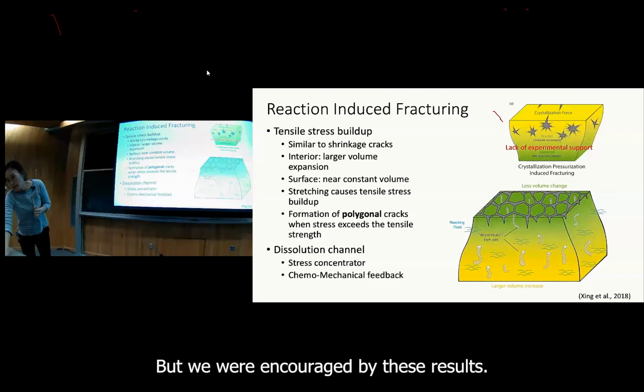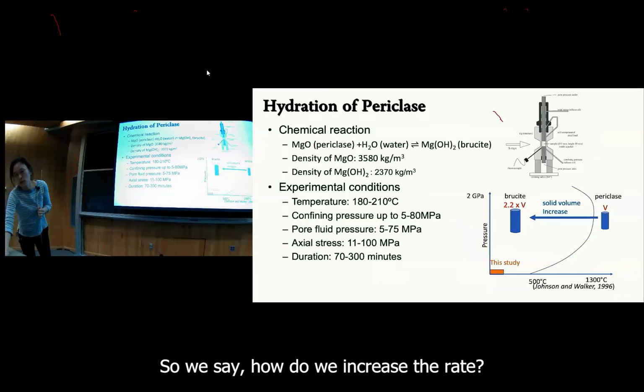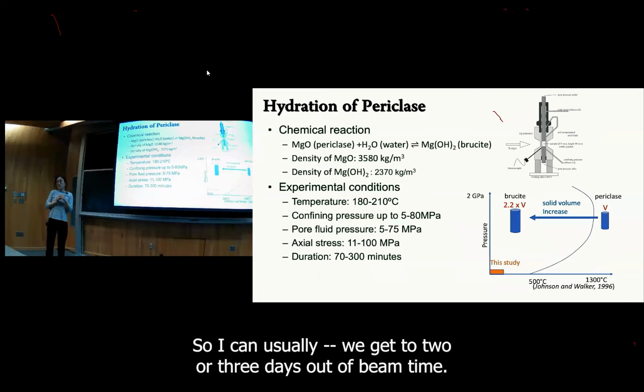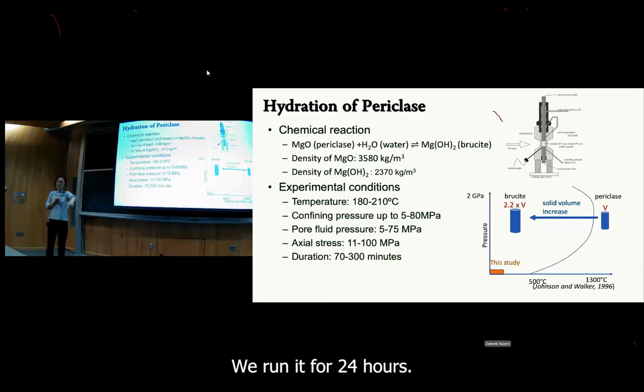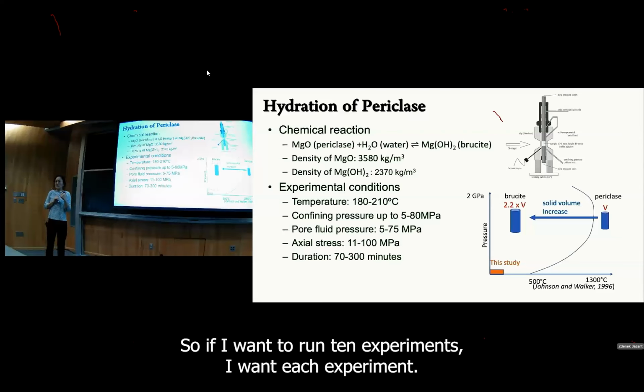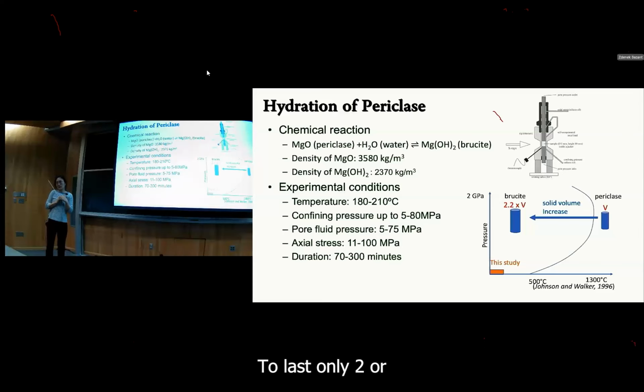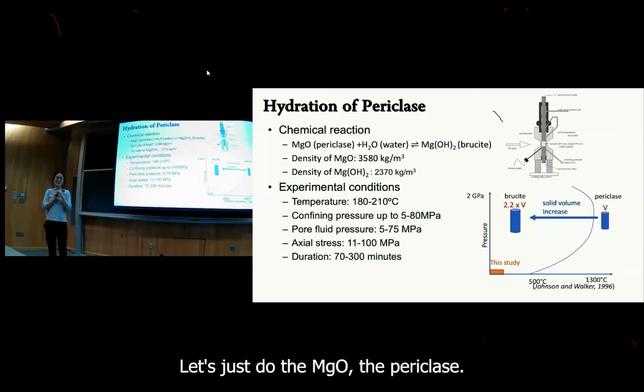But we were encouraged by these results, so we asked, how do we increase the rate? Usually we get 2 or 3 days of beam time. We run it for 24 hours. So if I want to run 10 experiments, I want each experiment to last only 2 or 3 hours. So then we said, let's not do olivine, let's just do the MgO, the periclase.